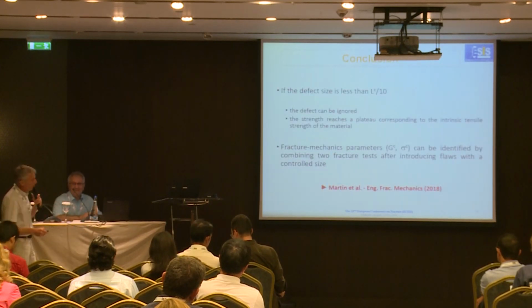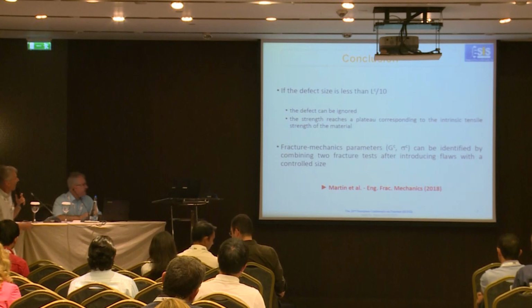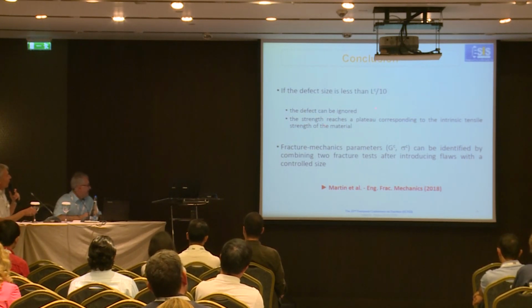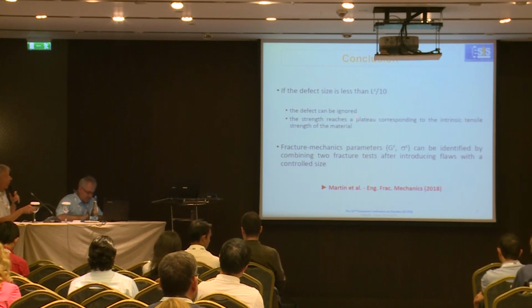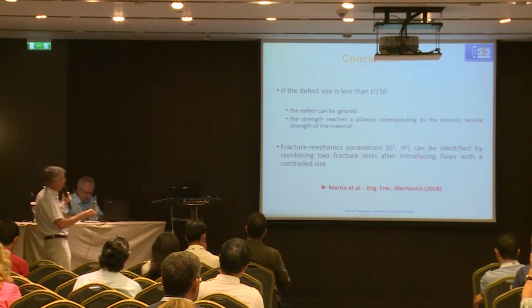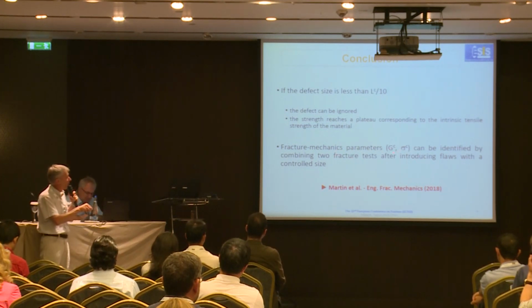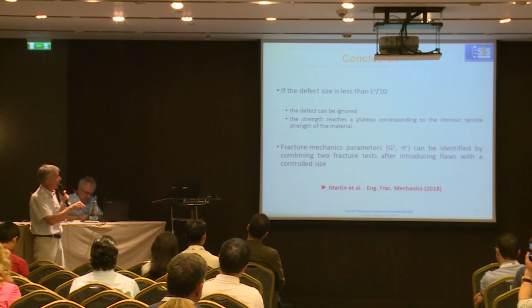Just to conclude the main result: for ceramic materials, if the size of the defect is small, you can ignore the defect, and it is possible to identify the fracture parameters from 2 experimental tests.